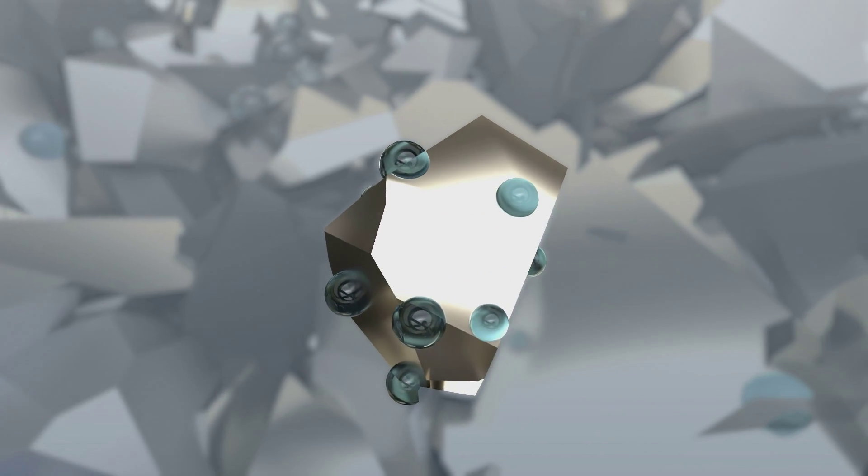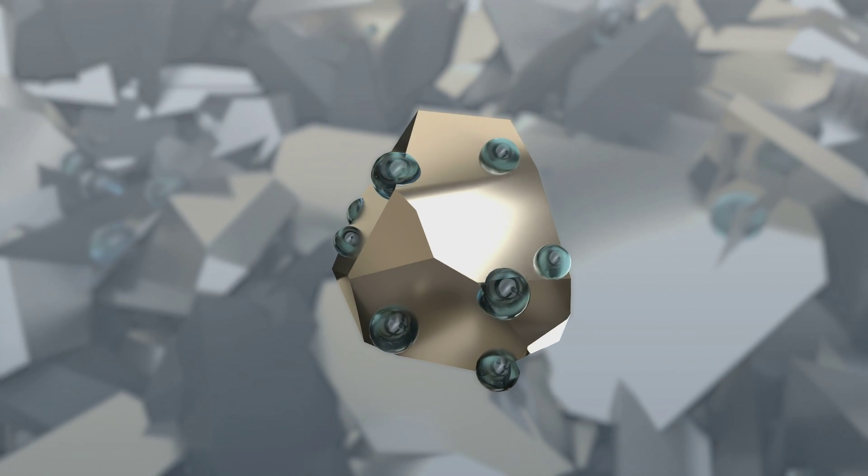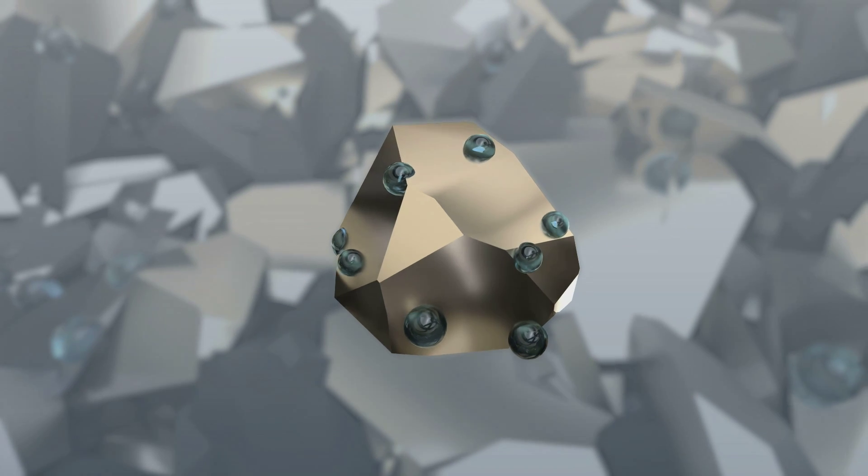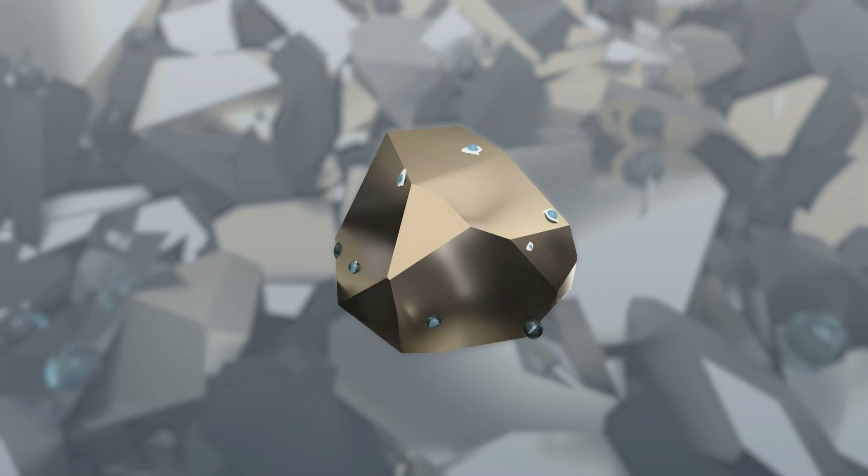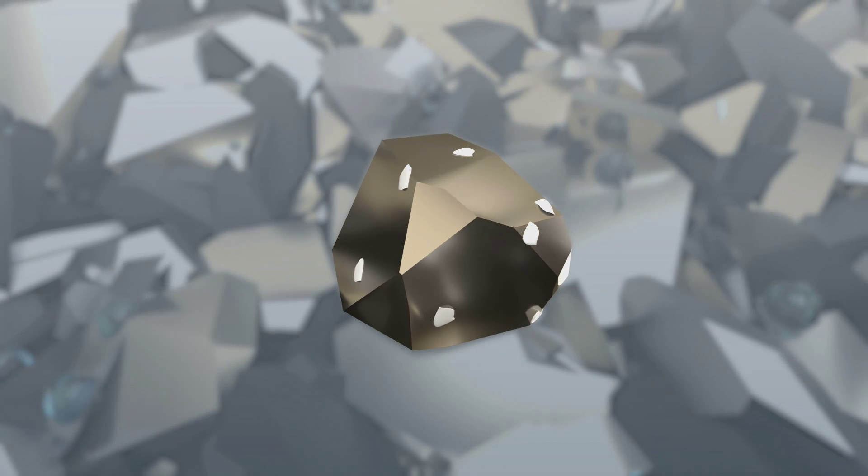In the vacuum dryer, there is a negative pressure of 300 millibar and a temperature held below 80 degrees Celsius. The electrolyte evaporates and the lithium precipitates as a result of this. And a lithium salt is formed on the granules.